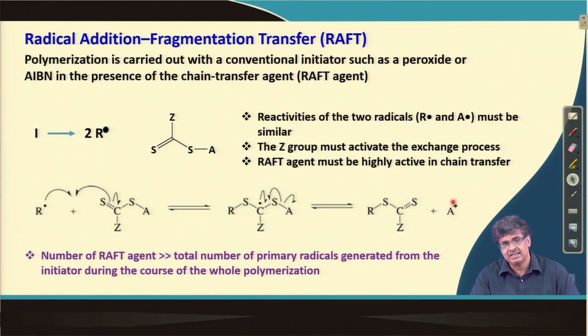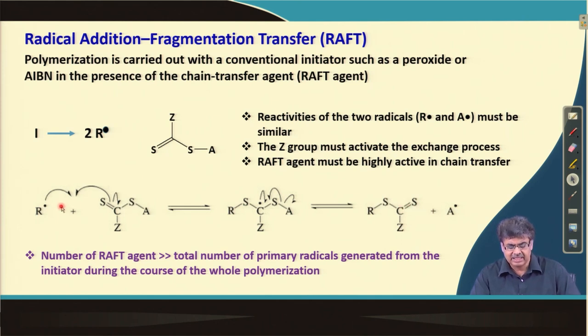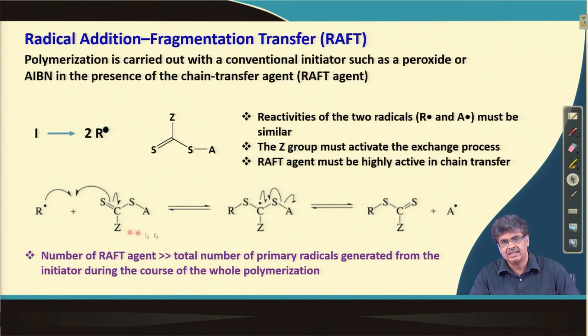The fundamental difference between RAFT polymerization and NMP or ATRP is that the active radical is not the original radical but one generated by the transfer process. This radical is not a stable or unreactive radical like in those other two examples — it can take part in polymerization, react with monomers, propagate the polymer chain, and also reversibly react with the RAFT agent. This is the origin of the name: radical addition fragmentation chain transfer.